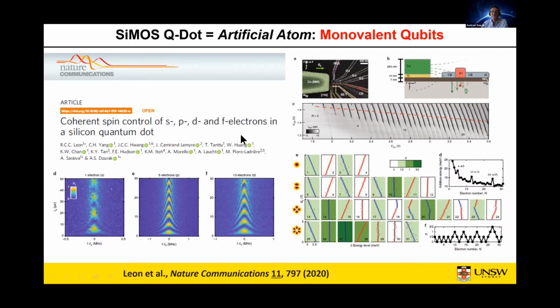And what he showed in this paper is that one doesn't have to settle with just single electron qubits. In fact, we can operate qubits with many more electrons than that. And the reason that this is important is that one of the challenges of using the CMOS platform is that the silicon-silicon dioxide interface is not stoichiometrically perfect. So there will always be disorder at that interface, and silicon dioxide itself is a quasi-crystalline amorphous material, which means that there will always be disorder, which can upset the potentials that we want for our qubits.